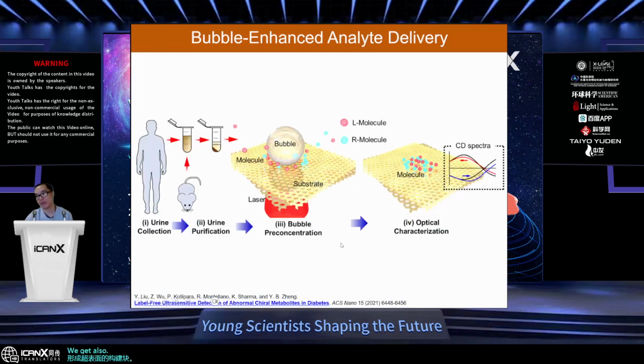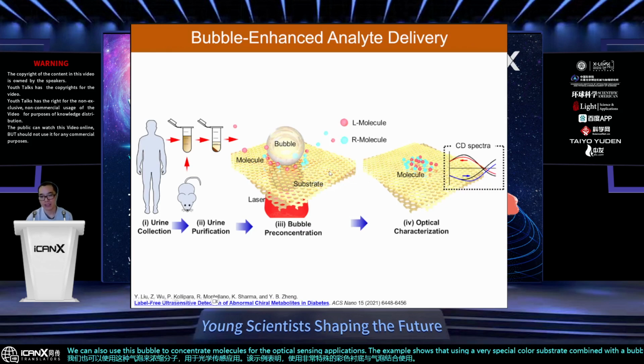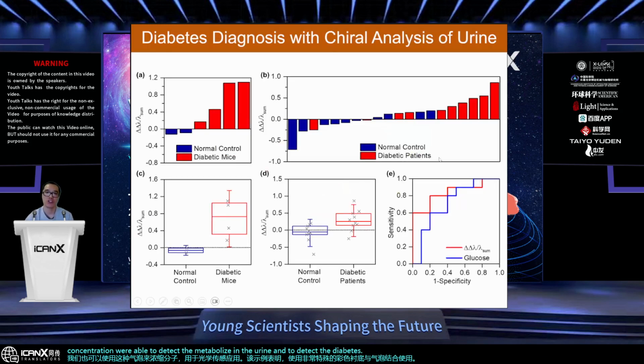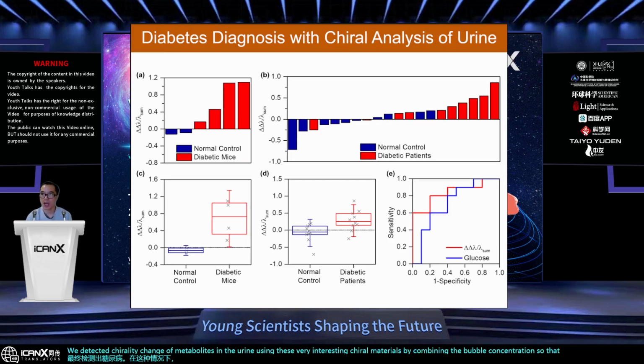We can also use this bubble to concentrate molecules for optical sensing applications. The example shows that using a very special chiral substrate combined with the bubble concentration, we're able to detect the metabolites in the urine and to detect diabetes. And we show that this can achieve a similar sensitivity to using glucose conventionally to detect diabetes. In this case, we detect the chirality change of metabolites in the urine using these very interesting chiral metal materials by combining the bubble concentration so that the throughput can be higher and the sensitivity can be increased because of